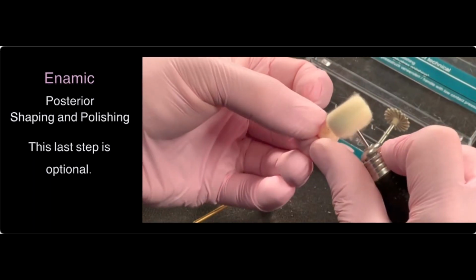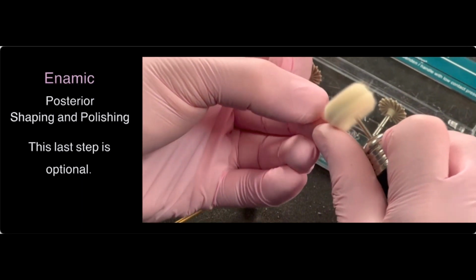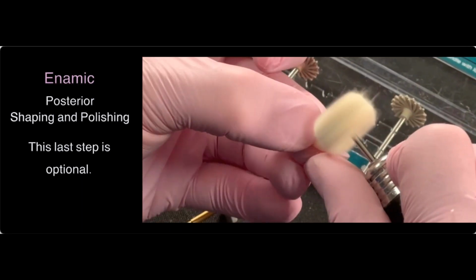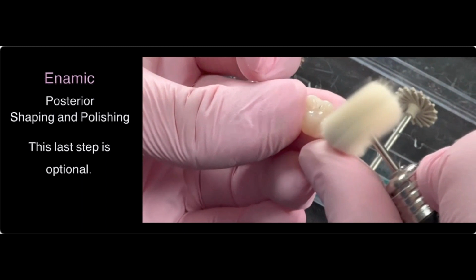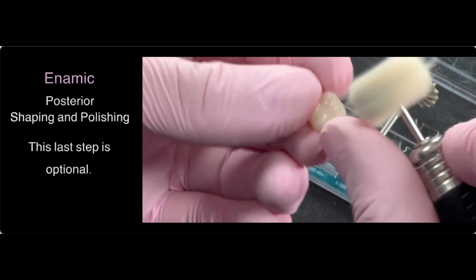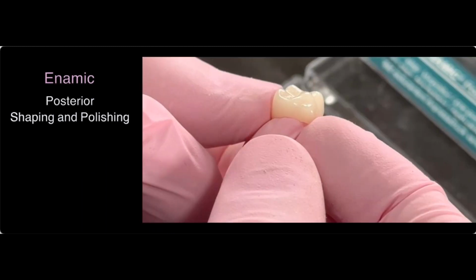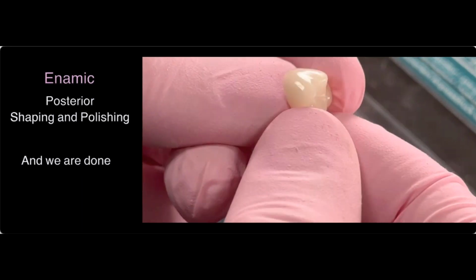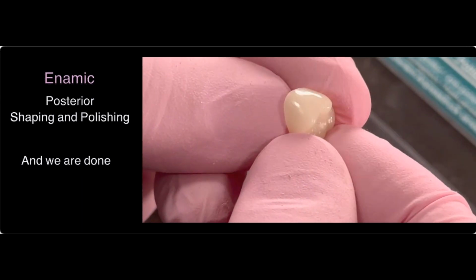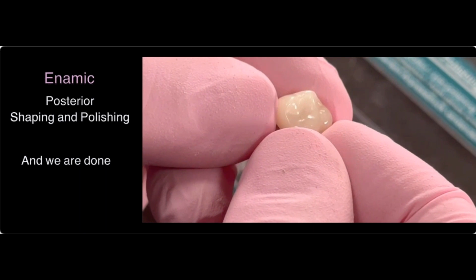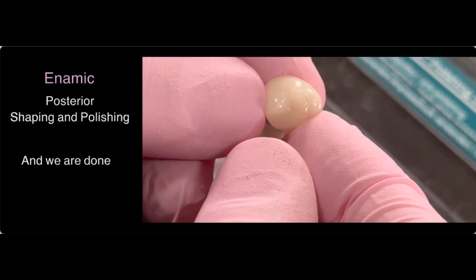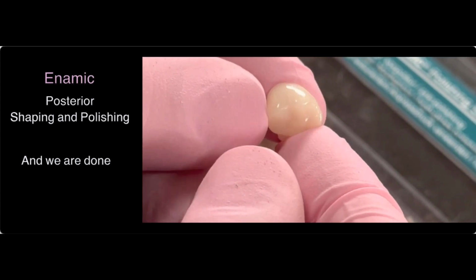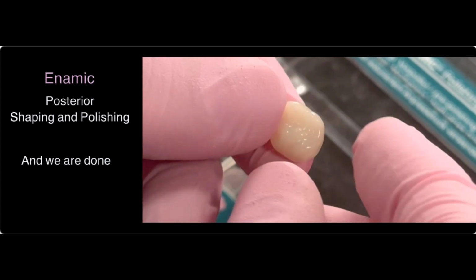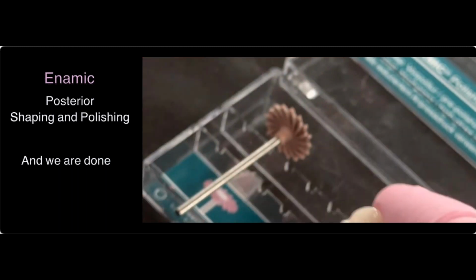It's going to be kind of shiny, but you shouldn't see any plane. When you look at the crown, you shouldn't see any scratch, because the last step, the shining step, the gray step, only makes things shiny like that. See, it's not going to remove any scratch. So people tend to jump to the last step too quickly when 90% of the time needs to be spent on the one that is not making it shiny, but the one that is making it smooth and soft. And then you can make it shiny. See that beautiful restoration you can do in about 10 minutes and ready to cement.